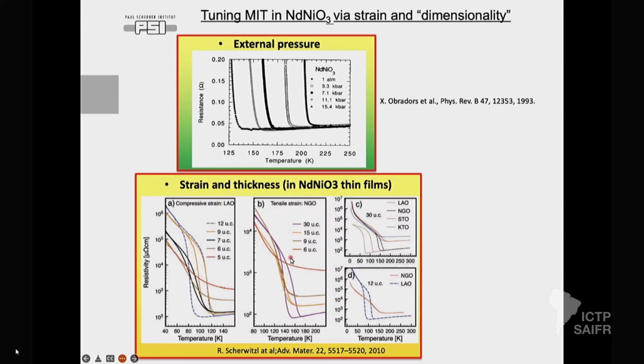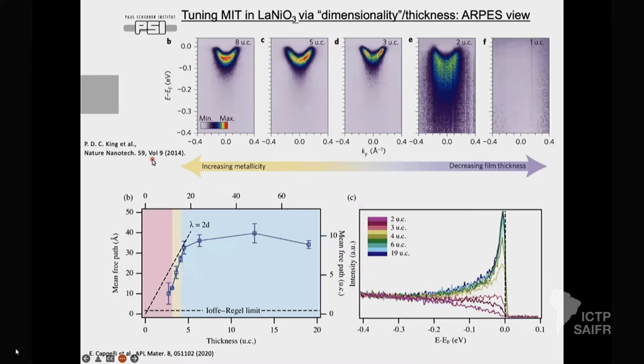So if you look at all of this data, there is something to conclude, because I have compressive strain, I have tensile strain, the effect looks more or less the same, besides that the temperature is different, but the effect is there. Lowering the thickness, the system goes to be an insulator in both cases. Of course, this is by transport, but there is a more sophisticated way to look at what can happen. Using angle-resolved photoemission, you can directly monitor the electronic structure of the system. And I will just here go a bit into the literature, and then later I will go a bit more into the global view, trying to actually show you what we see.